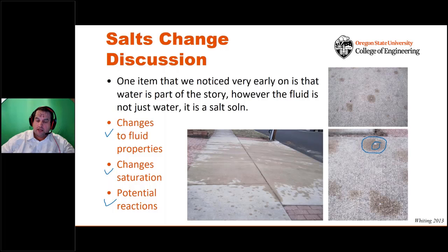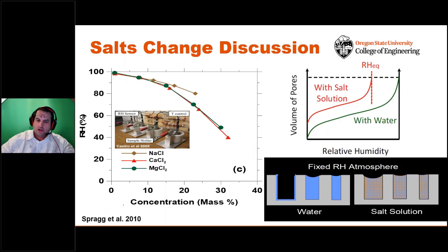The third item is we can get a potential reaction that takes place inside of the cementitious system. So just to show this and not to get into too much detail, if we look at relative humidity versus the concentration of salt, what we notice is there's an equilibrium point that we can see here for the three most common de-icing salts. And anytime we're below this relative humidity, we're going to suck water out of the atmosphere to try to raise the humidity level inside of the system.